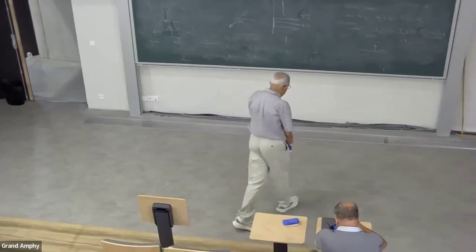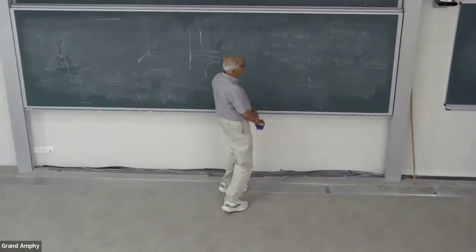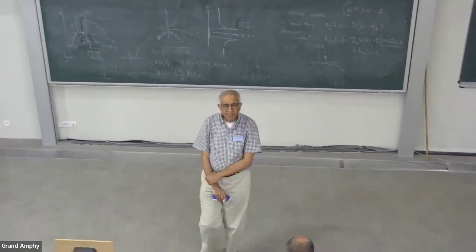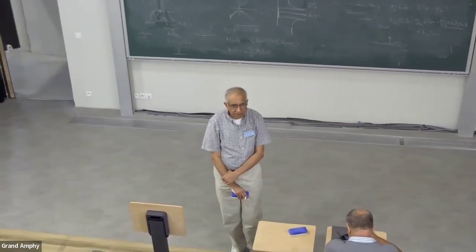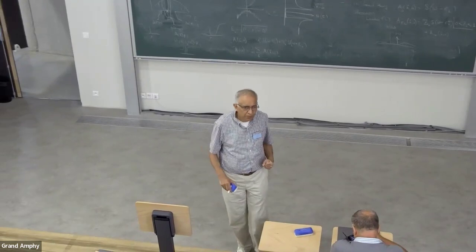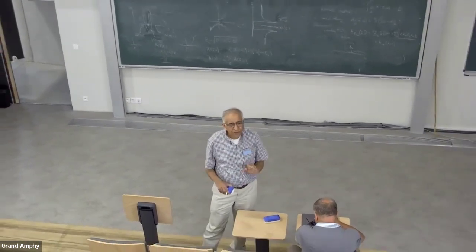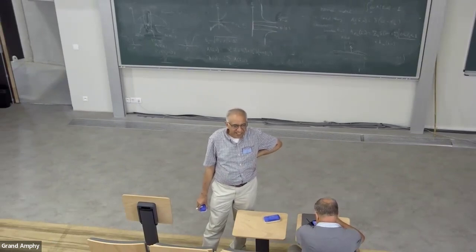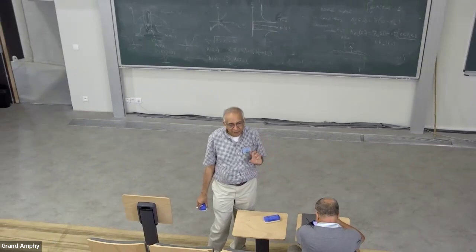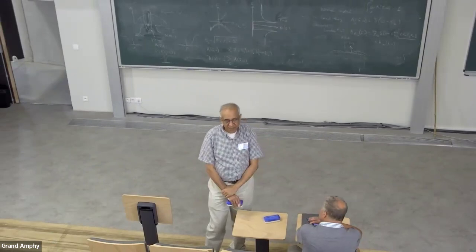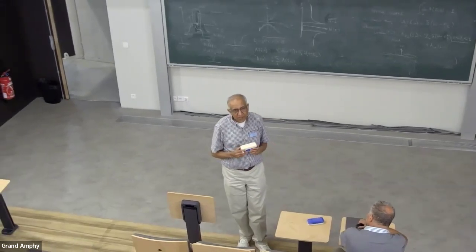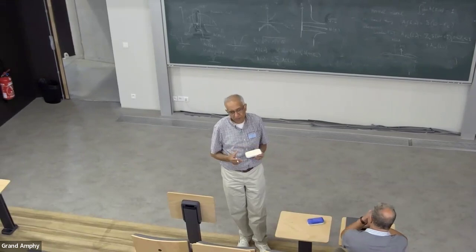Bogoliubov fermions. So the interesting thing about Landau Fermi liquid theory is that naive BCS theory is pairing real electrons. But if you really push someone, they'll say that actually we are dealing with the Landau quasi-particles. And so long as they exist, they govern all the important low energy physics of the problem. This is a very subtle and intricate point, which is usually not emphasized, but it's simply true.